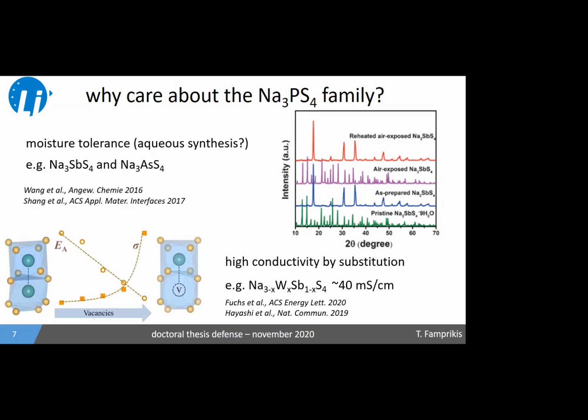And finally, the Na3PS4 family also contains the materials that are, let's say, the record holders for ionic conductivity in a polycrystalline form. And this was shown very recently through tungsten doping of the antimonate, which presumably introduces vacancies into the structure, increasing the conductivity to the levels of 40 millisiemens per centimeter.